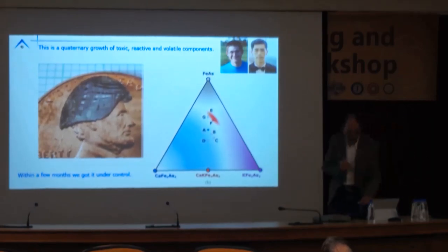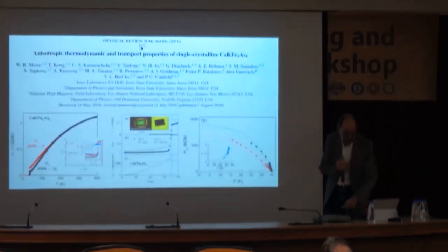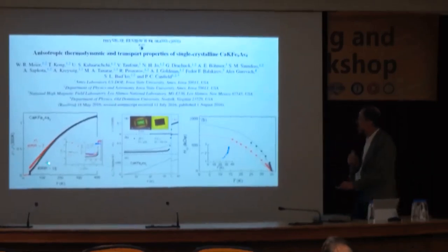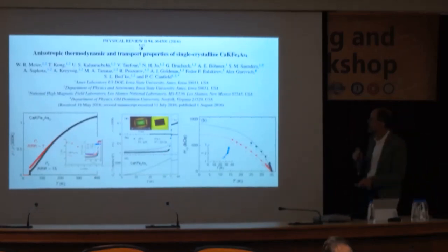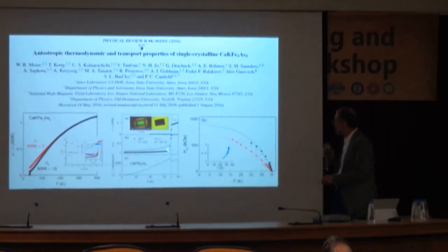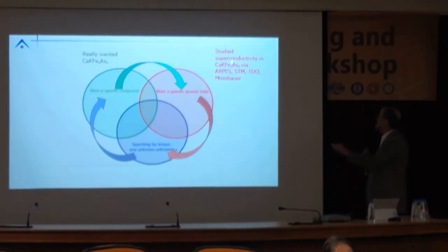And with single crystals, we can start looking at basic properties. Okay? So, we were able to measure the anisotropic resistivity, magnetization, expansion, and we were able to find that there's a beautiful and sharp superconducting transition at 35 Kelvin, confirming what Eo had found, at a slightly lower temperature in polycrystalline samples. We were also able to map out the anisotropic Hc2. We can see that it's similar to what we would anticipate for the electron doping of the barium. We were able to look at detailed measurements not only from transport, spectroscopic, ARPES, scanning tunneling microscopy,